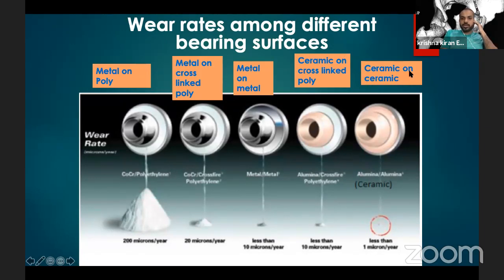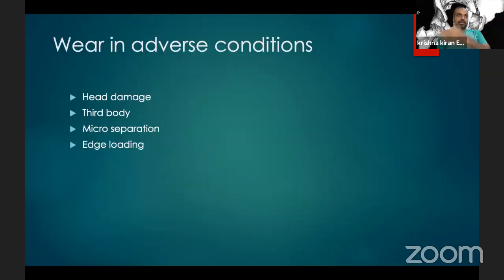And we have options of ceramic on ceramic, which is the hard on hard bearing, which has persisted predominantly because the wear rates are less than 1 micron per year. Cross-linked poly has brought down your wear rates to 20 microns per year or lesser. So you have almost eliminated the risk of osteolysis, because as we remember, osteolysis happens when the wear is 200 microns per year or more, and not when the wear is less than 100 microns per year.